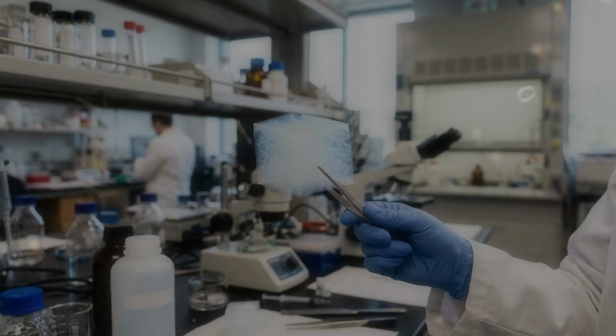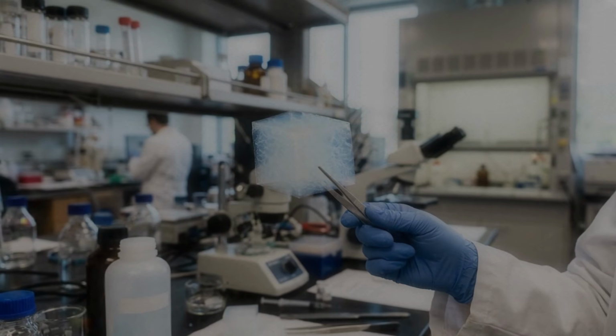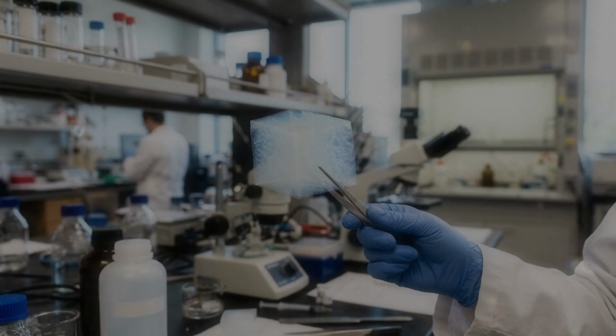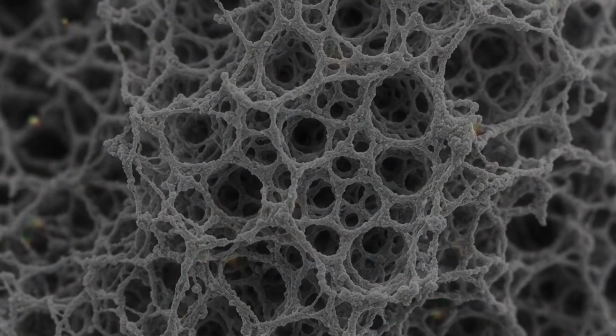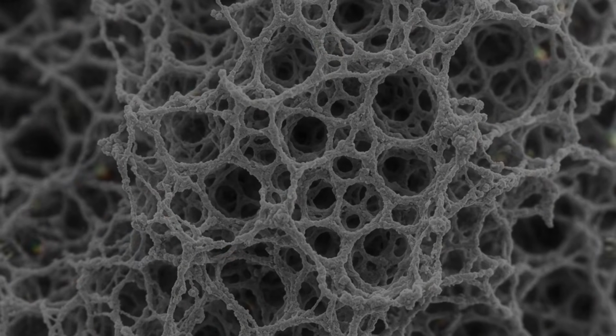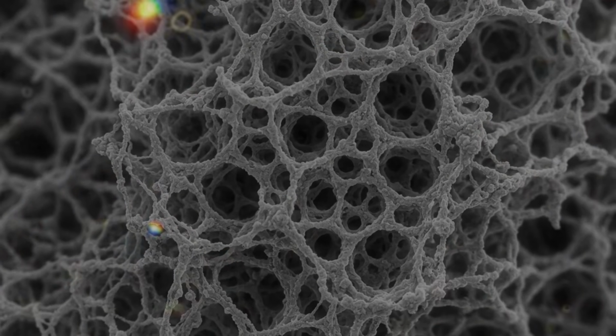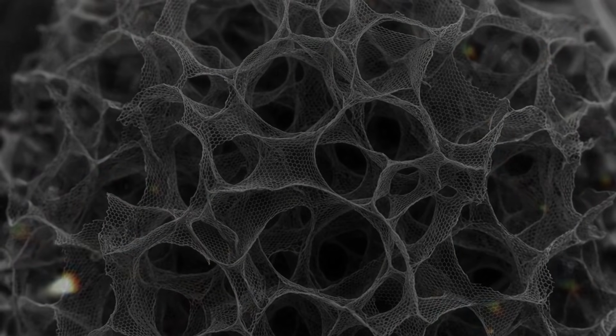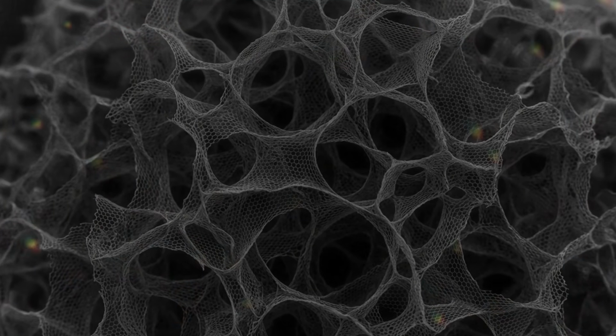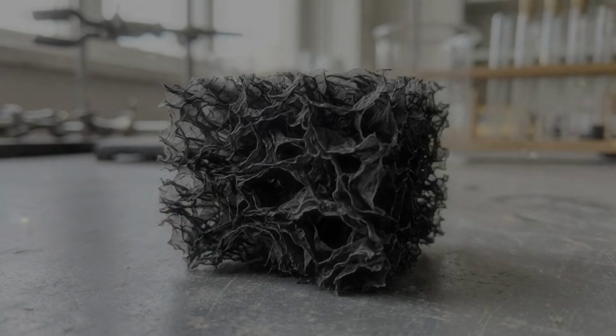Silica surfaces naturally contain chemical groups that can attract water and react with one another during drying. By replacing some of those groups with water-repelling ones, researchers can reduce unwanted bonding and help the network resist permanent collapse. The gel may shrink as the solvent leaves, then recover some of its original size afterward.